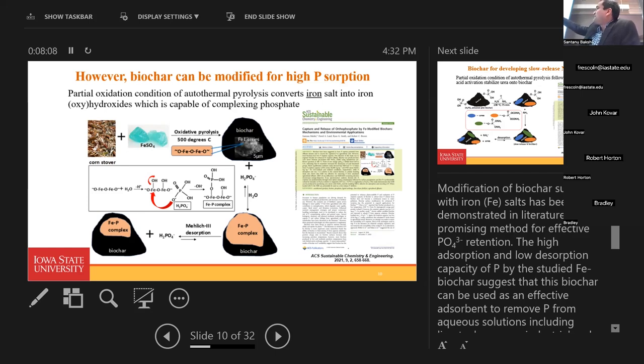What we did, we took corn stover and pre-treated it with iron sulfate and autothermal pyrolysis, which is also called oxidative pyrolysis. And we produced some iron phases on the biochar. After that, we did the phosphate absorption. And we have shown that this biochar is capable of absorbing more phosphorus and dissolving less phosphorus. On the right-hand side is the published manuscript, I think published in 2021.